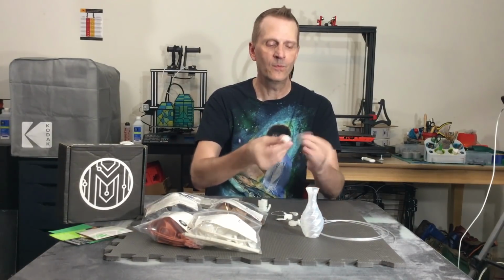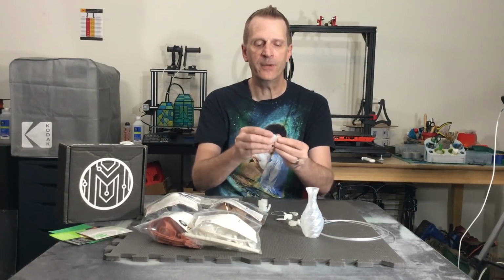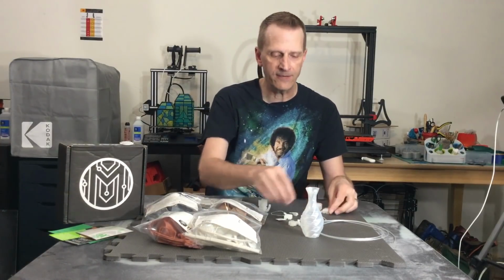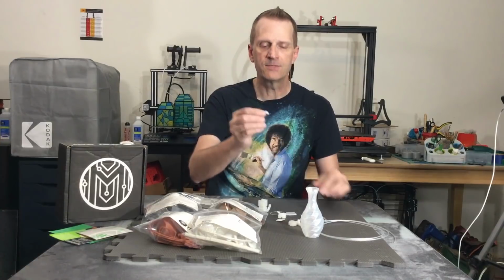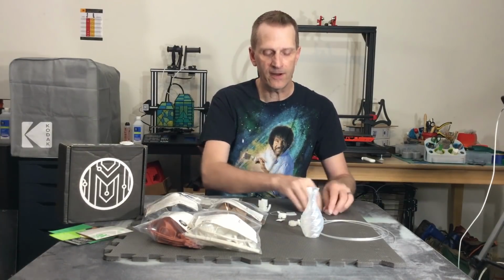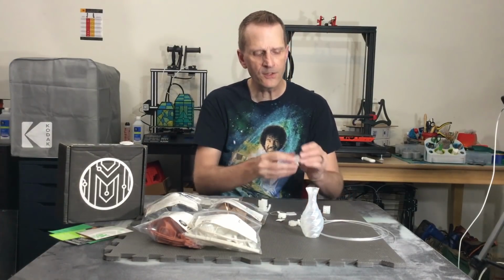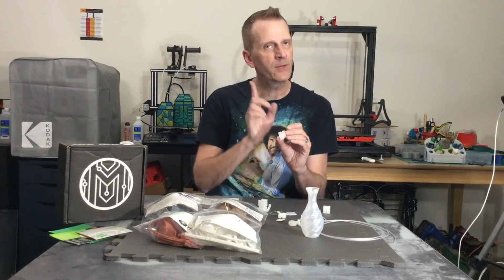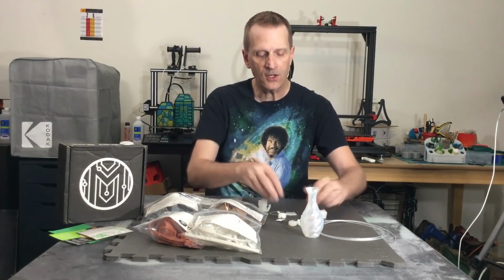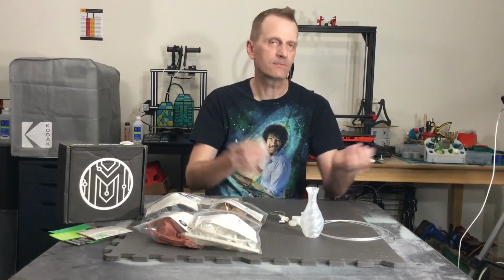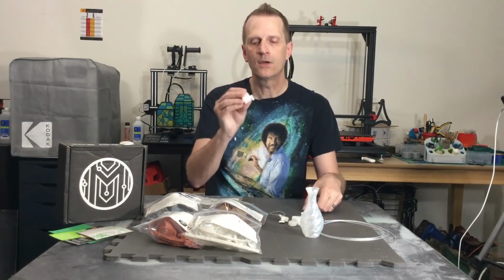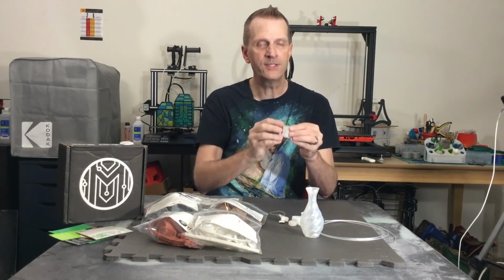There it is. But there was no layer adhesion. When I pulled it off the print bed, the head came right off immediately in my fingers, and then I just barely touched the tail piece and it broke right off. And I did notice that there was still a little bit of warping on the bottom, but it wasn't bad. So I decided to go ahead and use a raft, because that helps with bed adhesion. And we had a successful print all the way to the end.